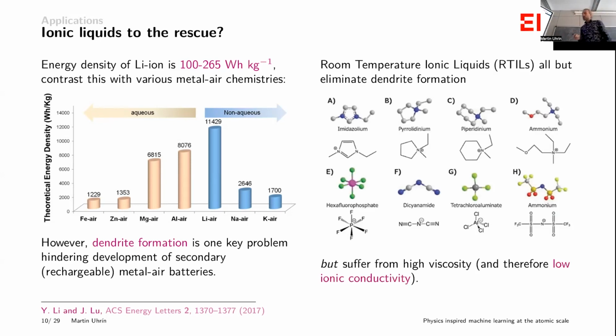And these room temperature ionic liquids have already been shown to almost entirely eliminate dendrite formation. So they seem like a very promising, viable candidate to use as your electrolyte. Now, what they look like is there are families of anion and cation molecules, and you can effectively play this nice game where you can choose a pair of these and just say, well, I'll make that into an ionic liquid, or I'll make these two into an ionic liquid, and just try and see what the properties of that system is. So for me as a machine learning guy, that's great because I've got this whole zoo of things that I can play with, put together, and then search for ones that maybe haven't been tried before.